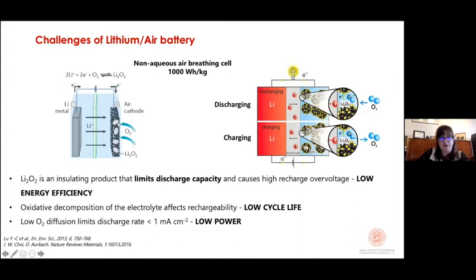During discharge, lithium peroxide is formed on these electrodes, and lithium peroxide is an insulating component. So the formation of lithium peroxide limits the discharge capacity, but also causes high recharge overvoltage, and then typically affects a low energy efficiency of the system. Not only that, high overvoltage brings about high recharge voltage that in turn may impact the oxidative decomposition of the electrolytes, and then affects cycle life.